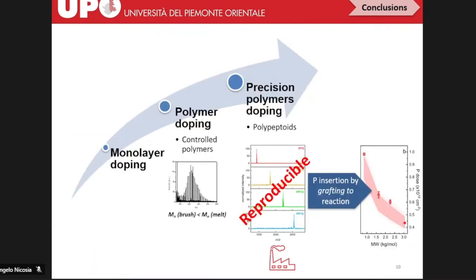So as a conclusion, we moved all the way from monolayer, using the technique of monolayer doping, to controlled polymers, and then precision polymers, and we found a strategy that allows us to have polymers that are reproducible. We are able to adapt this strategy at an industrial level. We are able to insert phosphorus, so maybe we can say that we are one step closer to the deterministic doping of semiconductors.